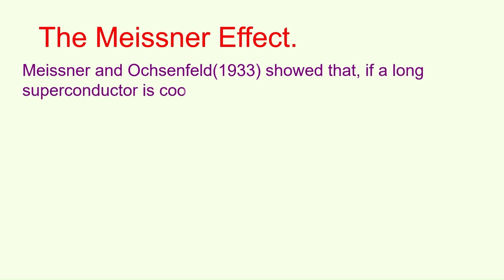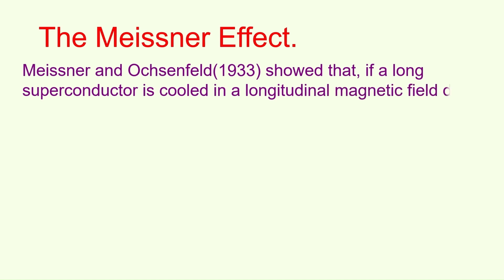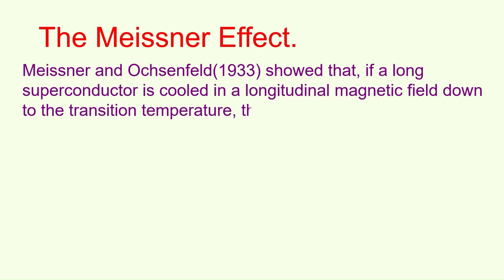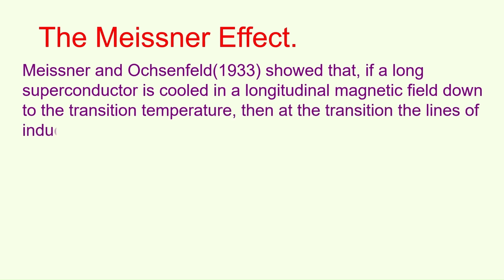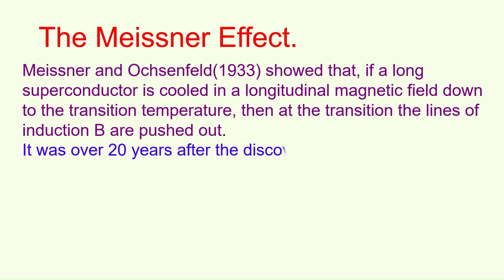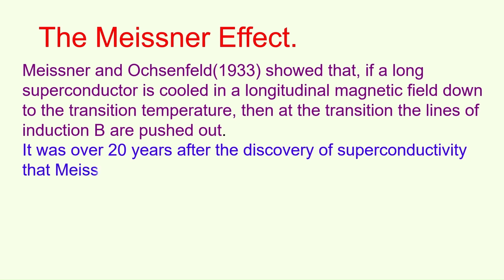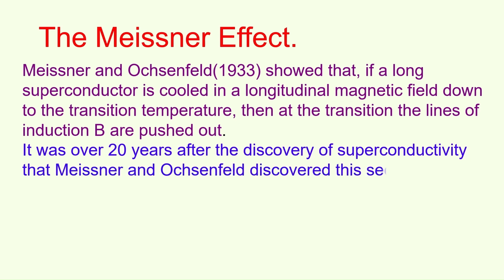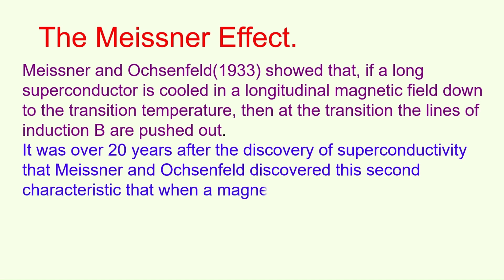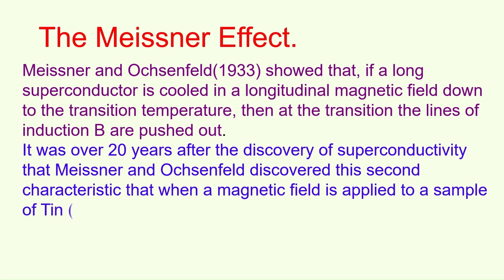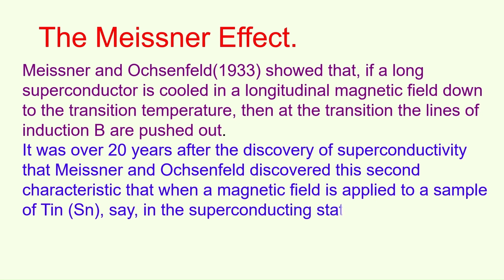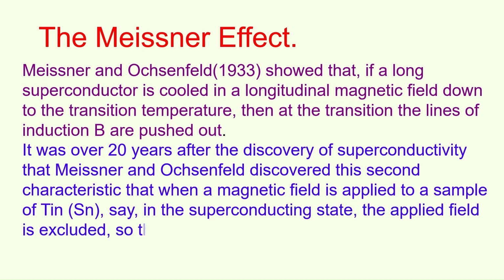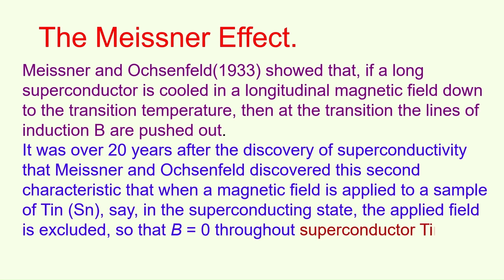The Meissner effect. Meissner and Ochsenfeld in 1933 showed that if a long superconductor is cooled in a longitudinal magnetic field down to the transition temperature, then at the transition, the lines of magnetic induction are pushed out. It was over 20 years after the discovery of superconductivity that Meissner and Ochsenfeld discovered this second characteristic, that when a magnetic field is applied to a sample of tin, Sn, in the superconducting state, the applied field is excluded, so that B equals 0 throughout the superconductor.